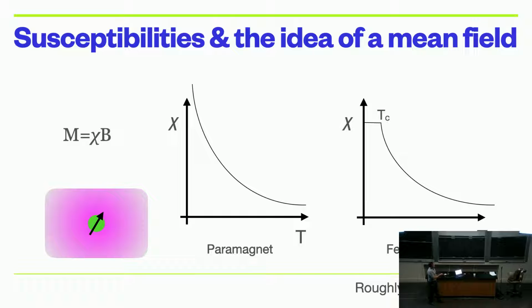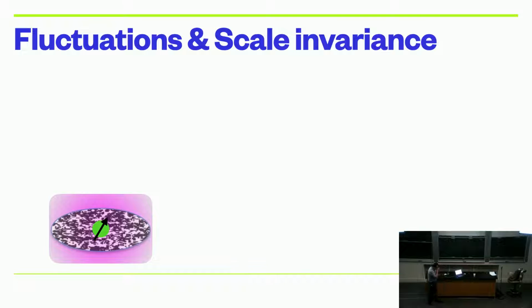Roughly speaking, and this is not quite accurate, before the condensed matter physicists growl at me, the transition temperature at which your system goes ferromagnetic is proportional to the exchange energy scale. So the interactions between your spins are roughly proportional to wherever the system orders. If you've got a room temperature ferromagnet, it has strong interactions; a ferromagnet at like 5 Kelvin usually has much weaker interactions. Sometimes it means other things, but we'll get to that later. Okay, so how do we characterize what this mean field is?